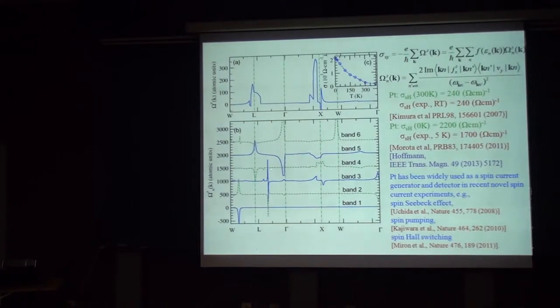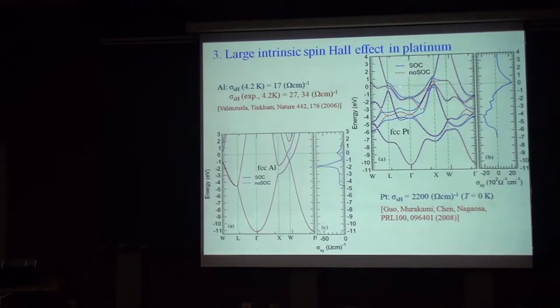And then, we have one occupied that gives rise to negative Berry curvature here, and then give rise to peak in the Brillouin zone at the L point, and similar occurring here. So, now we understand that the Fermi level in platinum is occurring at the spin-orbit split and gives rise to huge spin Hall conductivity.